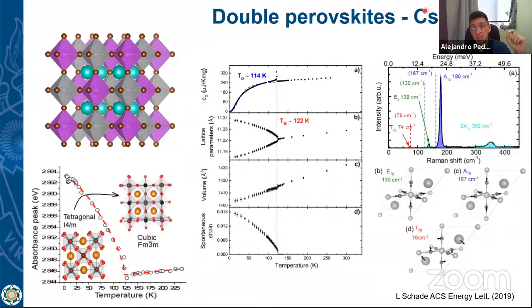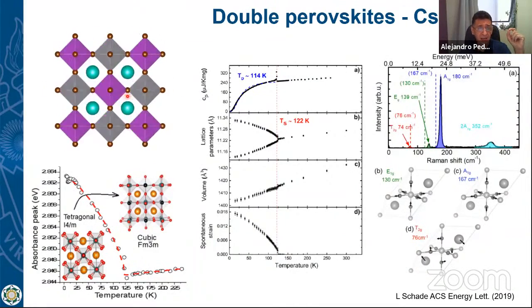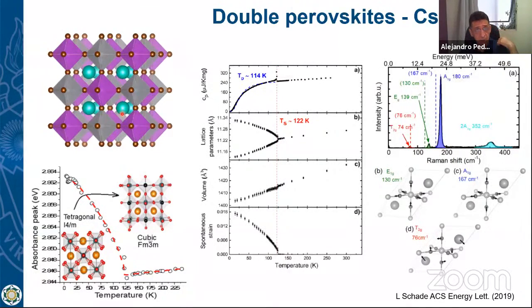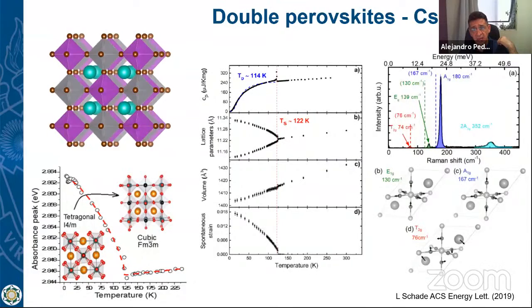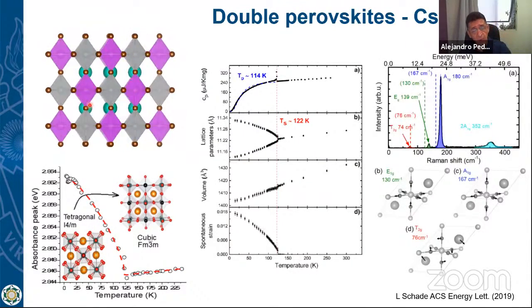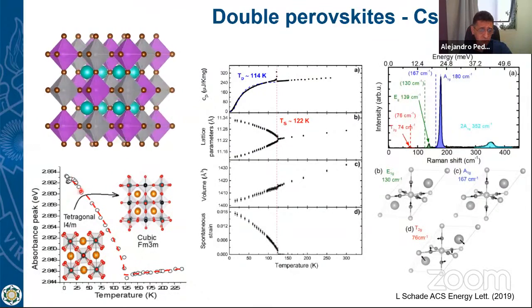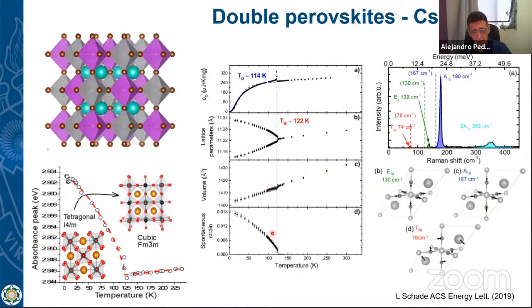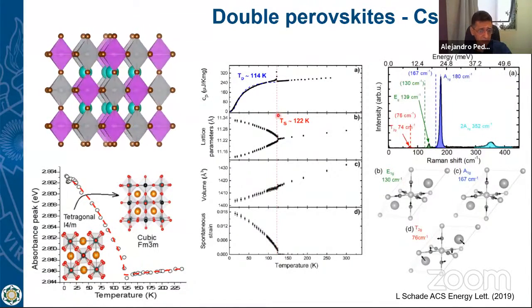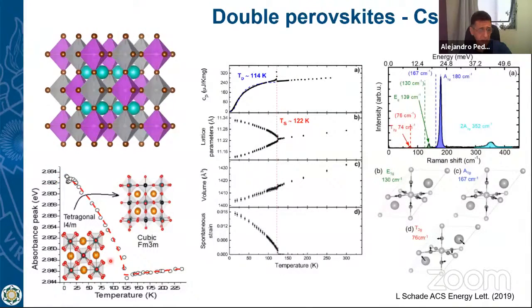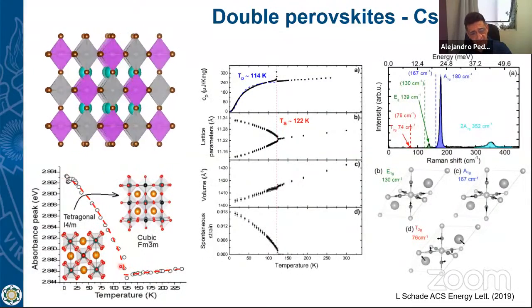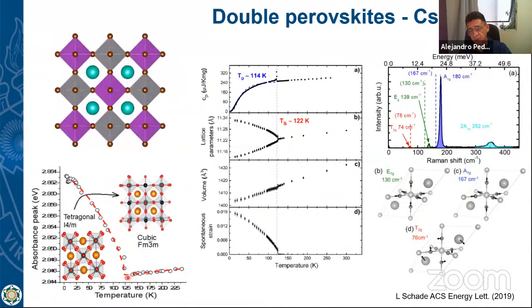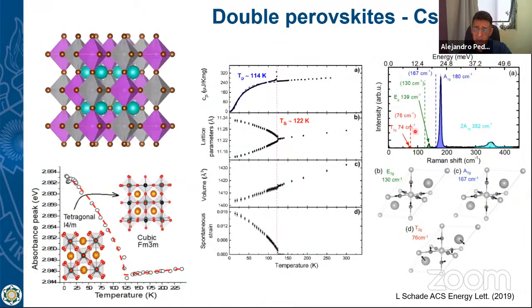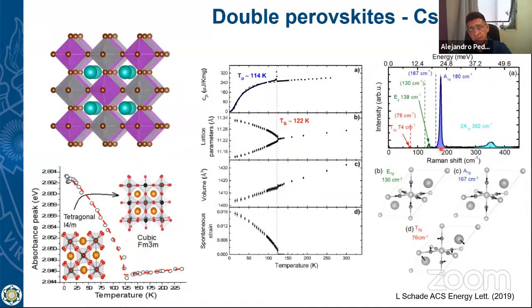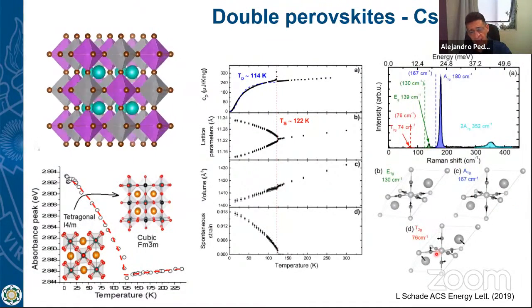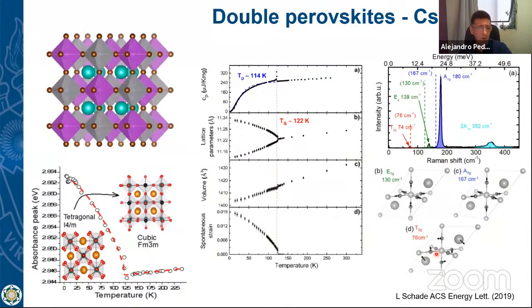So in this perovskite, which is a lead-free perovskite, we have a so-called double perovskite structure because the two atoms inside of the halide octahedra are intercalated. And X-ray diffraction showed there is a structural phase transition around 122 Kelvin. The photoluminescence, or the absorbance of the light, also shows a change at this point. And if we calculate the Raman spectra, we can associate the different bands to the different kinds of movements of the cations and anions in the compound.